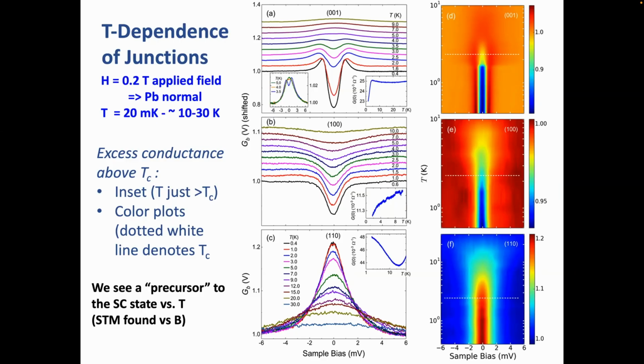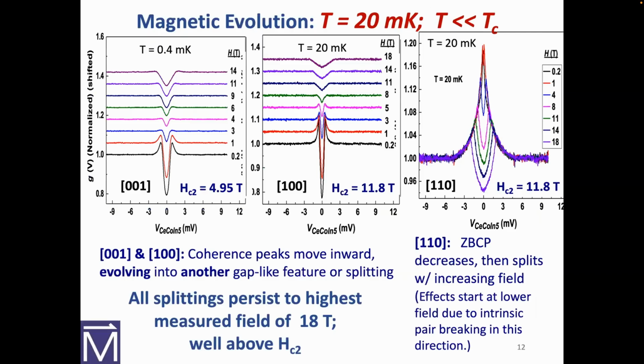All I want you to take away from here is, if you look at those lines, the dashed white line across all three of those color plots is where Tc is. And the takeaway is that above Tc, this is not a Fermi liquid. Something's going on. If you look in any of these directions above Tc, something's happening. A pseudogap, who knows what, stripes, anything. It's just non-Fermi liquid, and we know that for sure; it's very, very reproducible.